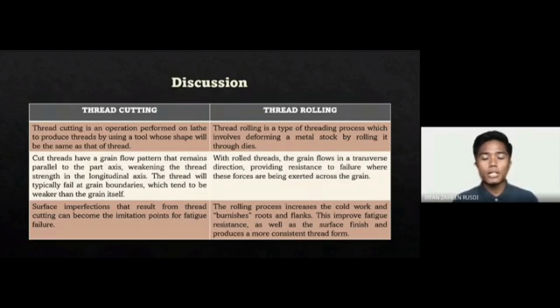While in thread rolling, with rolled threads, the grain flows in a transverse direction, providing resistance to failure where these forces are being exerted across the grain. Surface imperfections that result from thread cutting can become the initiation points for fatigue failure. In thread rolling, the rolling process increases the cold work and burnishes roots and flanks. These improve fatigue resistance as well as the surface finish and produce a more consistent thread form.